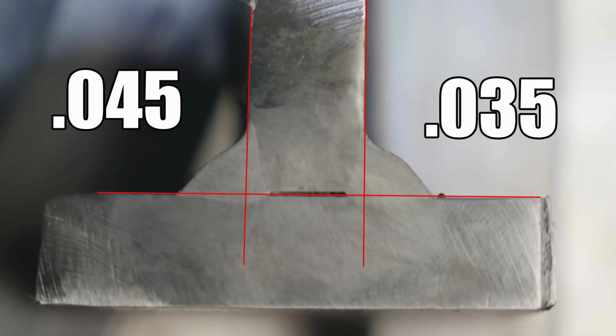Here's a cross section of how the weld's penetrated on that half inch thick plate. And I wanted to check it out since I'm running short circuit MIG on thick steel to make sure that it did penetrate down into the joint. And in this case, it dug in pretty good.